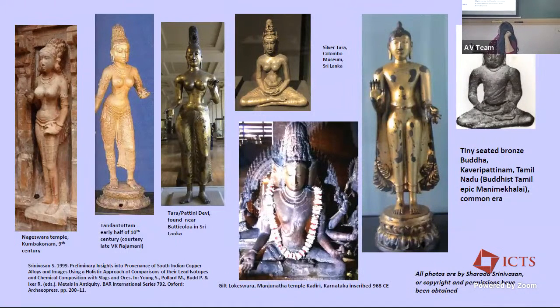This is also to point out that there are two very interesting bronzes that I had also analyzed for lead isotope ratio analysis. One of them I discussed yesterday, and I talked about how this was made by the mercury gilding process, and the fact that this is by and large a copper image with just 1% of lead. That's also quite sensible because lead is not a very good element to add if you're doing mercury gilding, because the mercury amalgam that you apply with the gold, you then have to burnish it to burn off the mercury.